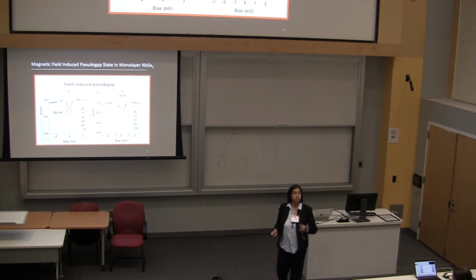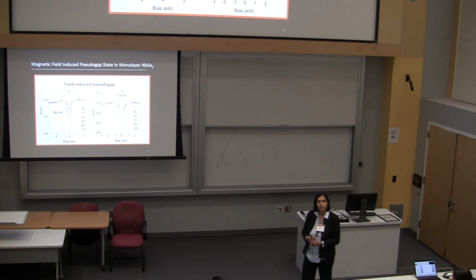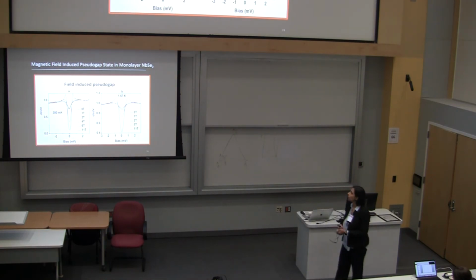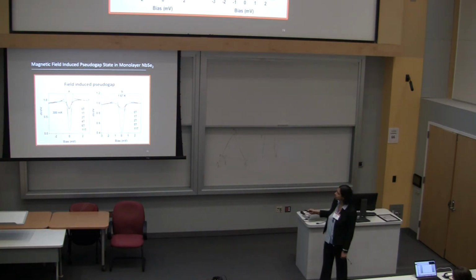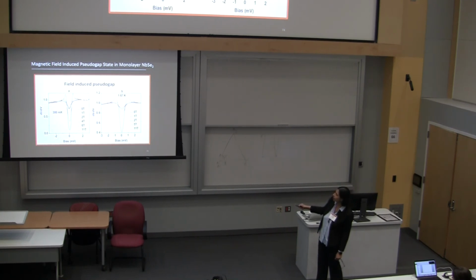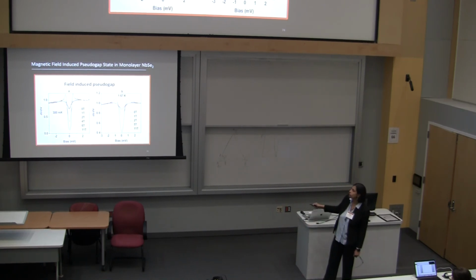The interesting observation that we made is the following. We turned on a magnetic field, and what we found is the following. Look at this. We're marching through different fields: 0, 1, 2, 3 Tesla, and so on. You go from 0 to 1 Tesla, the bottom of the gap lifts up, the coherence peaks are suppressed, that makes sense. You get to 2 Tesla, same thing, the bottom lifts up some more, the coherence peaks are suppressed some more. But beyond 2 Tesla, 4, 6, 11 Tesla, there's no change.